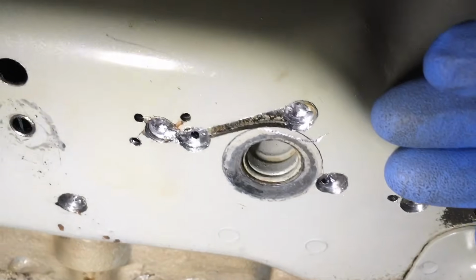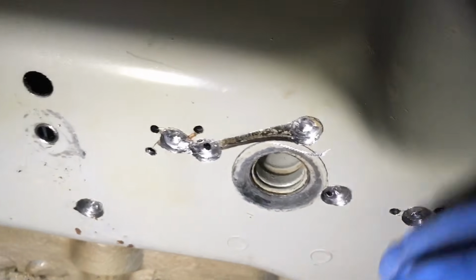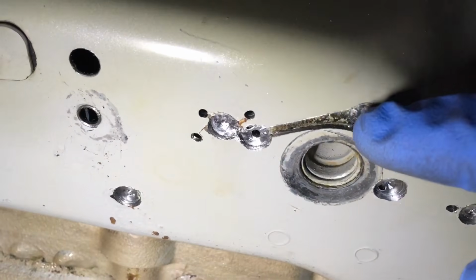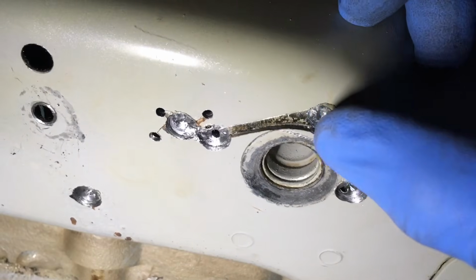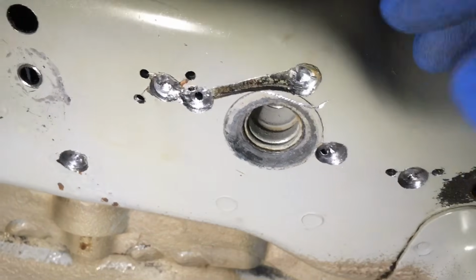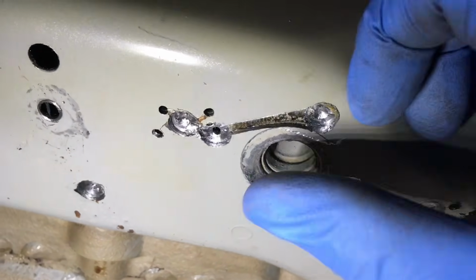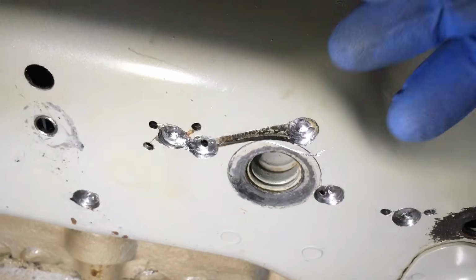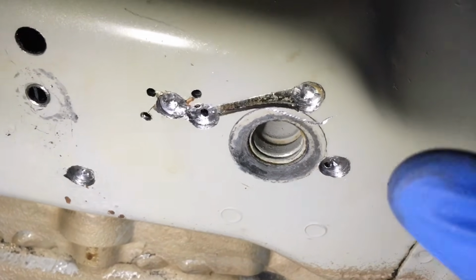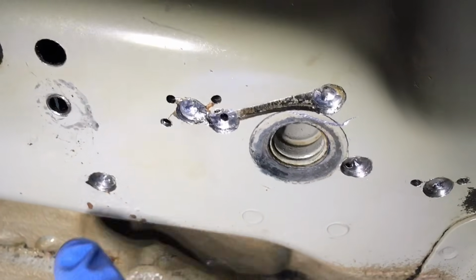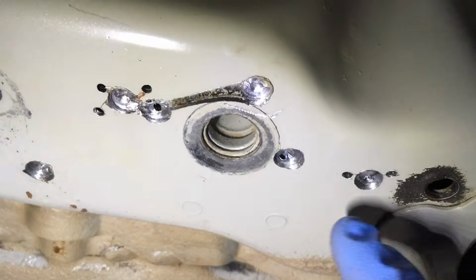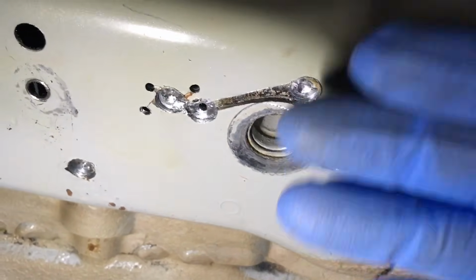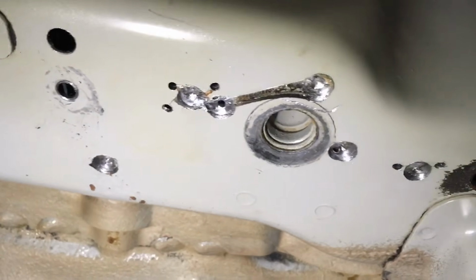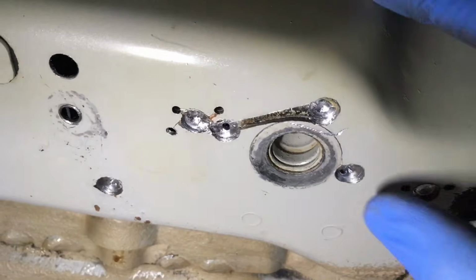So that not only gets rid of the crack, so it's not a problem in the future, but then when we weld that channel up, we penetrate on the 2mm threaded receiver platform inside, and then join it to this outer rear axle carrier panel skin, and that strengthens the connection point between those 2 pieces of metal, because other than that they're relying on just 5 of these spot welds, which are problematic anyway. So we greatly improve the strength of the 2 pieces, as well as removing the crack risk as well.